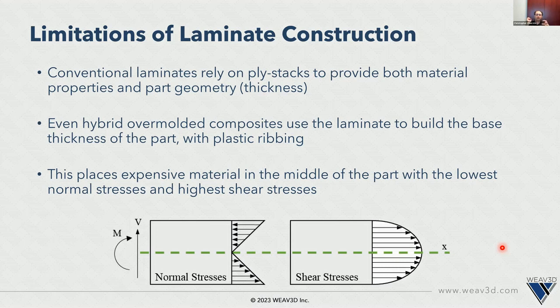So if you then overmold that laminate with ribs, you're effectively putting a cheap material on top of a very expensive material, and that expensive material is still making up the bulk of your cross-section in the part, which means you've got a lot of expensive material sitting in the mid-plane, around the neutral axis, and it's not fully being utilized to carry the normal stresses in bending, the tensile and compressive stresses that it really wants to carry. Rather, it's being loaded with shear stress, which for laminates is a problem because they want to delaminate when subjected to severe interlaminar shear.